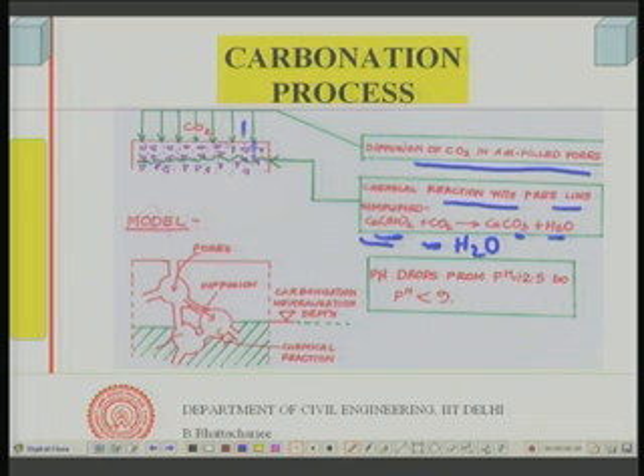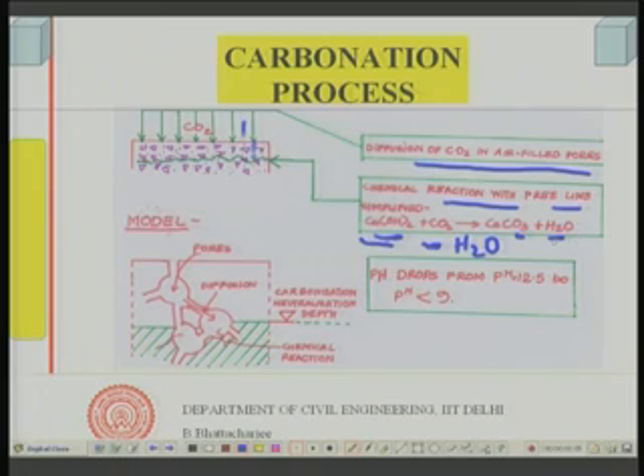Once a layer of calcium carbonate has been formed, carbon dioxide will actually diffuse through that layer, and then the reaction will proceed below that layer of calcium carbonate. The carbonation front, as we call it, proceeds from the surface to the inside of the concrete, and up to this point the carbonation front has now reached, where this reaction continues. Of course, there are intermediate reactions, because normally there will be calcium hydroxide reacting with the carbon dioxide forming calcium carbonate, then reacting further, but the final product is like this.